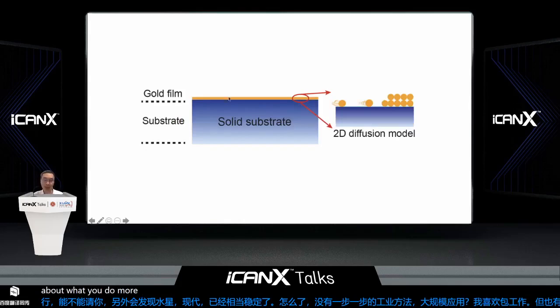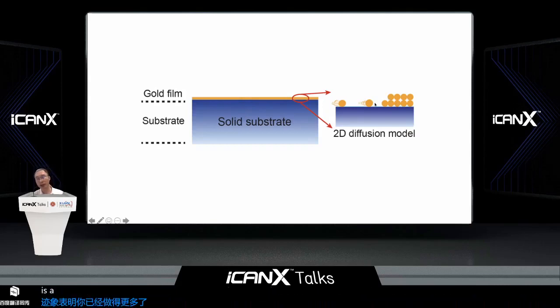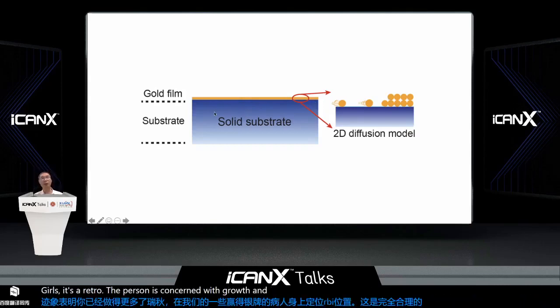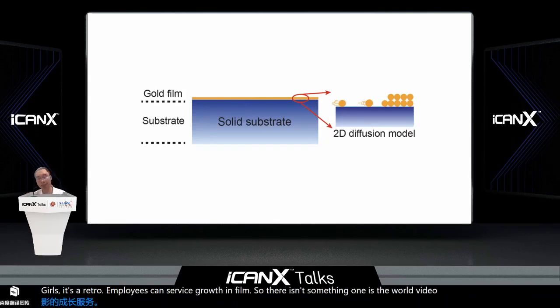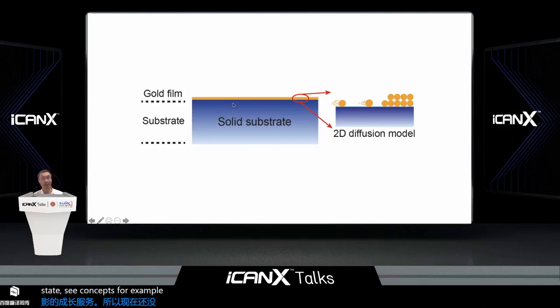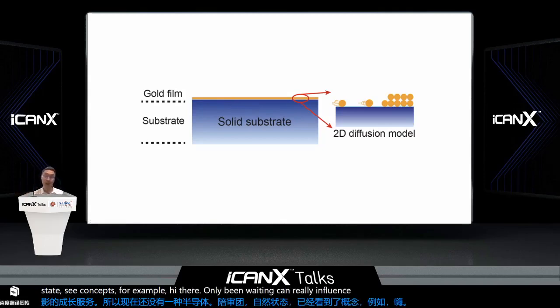We know that metal deposition normally uses e-beam deposition or thermal evaporation and so on. The film on the surface grows two-dimensionally: metal deposits on the surface and forms a continuous film. This is widely used in semiconductor technology. With metal on a solid-state silicon substrate, for example, you can only embed a few angstroms, less than 1 nanometer, inside. In this case, as I just said, it is easy to peel off.